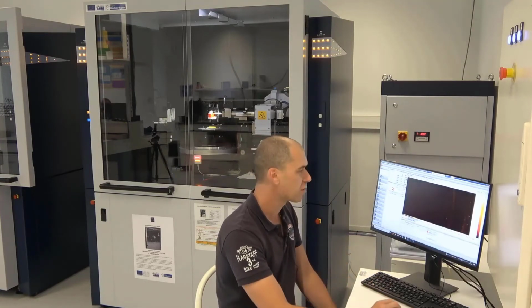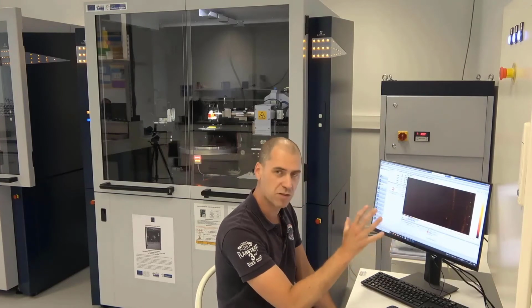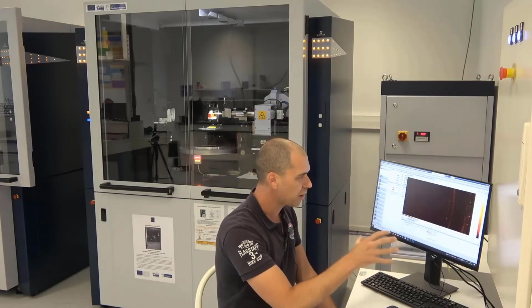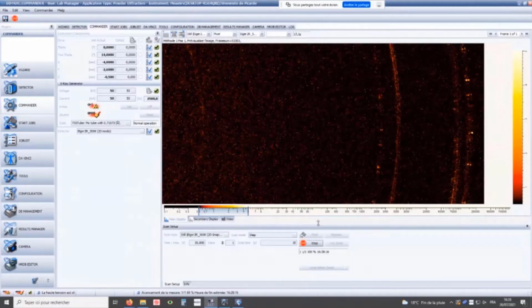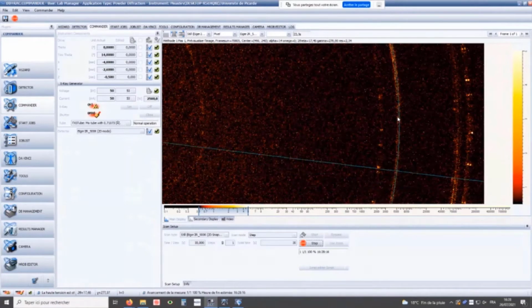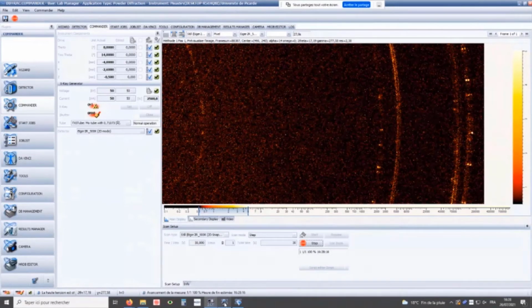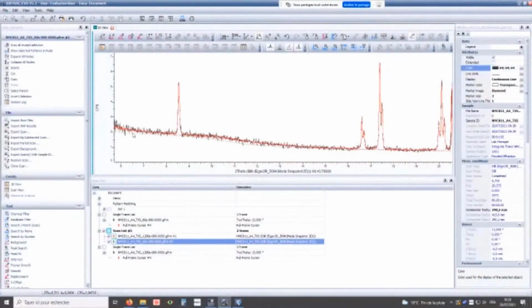So the snapshots allow us to stay at the same place and collect data in a very fast way. So we can see live the Debye rings popping up on the screen, which will then be integrated using EVA. So using EVA, we can see here two different patterns which have been measured. The black one has been measured in a minute on the very same material which is running right now in the diffractometer. And the red pattern has been measured within 20 minutes.